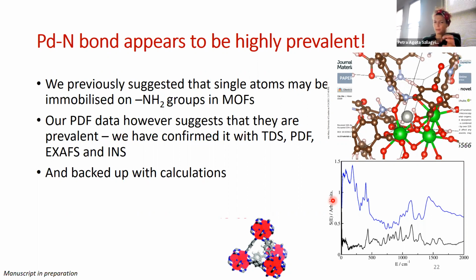Sorry, first, you mean, I suppose, the palladium particles dispersed throughout the MOF particles rather than the size distribution. So we didn't really see any sort of conglomeration of particles, so we assume that it's fairly random. To really tell that, we would need to do a proper MOF particle size dependent study, trying from really small MOF particles and making as large crystallites as possible, and doing the same kind of testing through that. But we haven't done it yet. We've seen no evidence of it not being random.